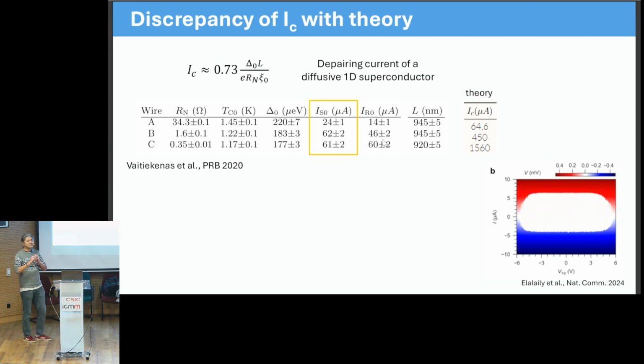But the fact is that this is a superconducting nanowire, and the critical current that this wire can carry is limited by different effects, but normally in the absence of perturbations, it will be limited by thermodynamics, so it will be the pair-breaking current that you can run. And this can be described by theory. Now, when we compare this to experimental results, what one can see is that the experimental critical current of these wires is much lower than what one would expect from theory. And it doesn't seem to correlate at all with, because this essentially depends on dimensions or geometric factors, apart from the type of superconductor. There's absolutely no correlation.